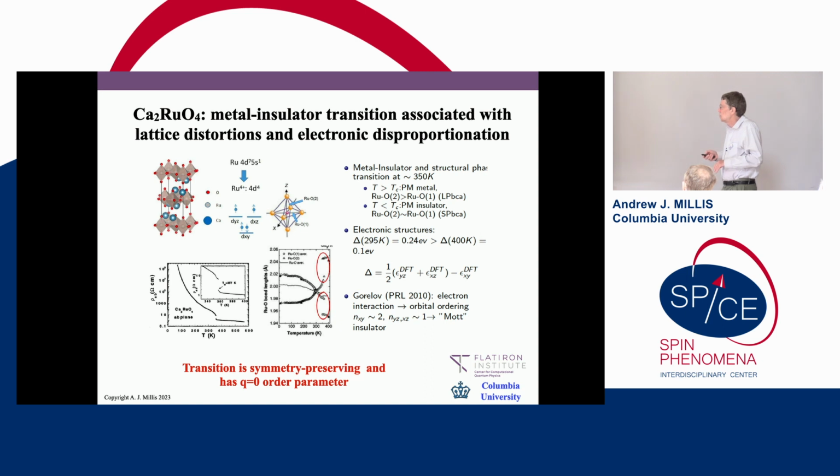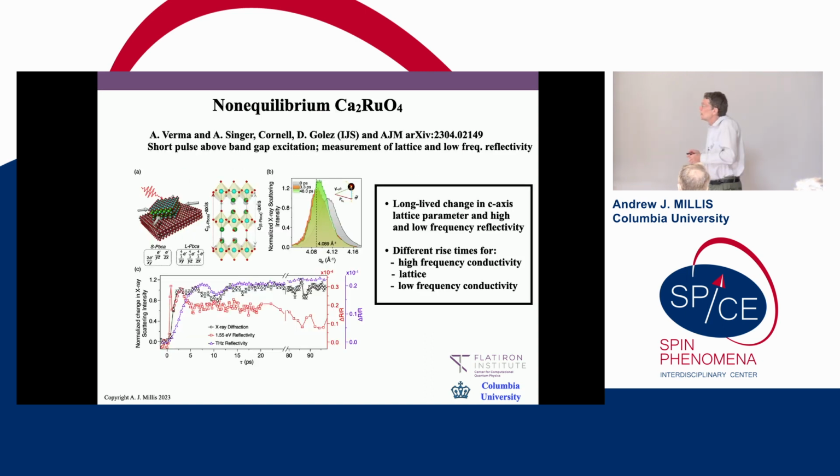Okay, so that's equilibrium. Now, what Andre and his student or postdoc, I forget which, Anita, did, and it's explained in this paper, which is primarily an experimental paper, is again, they excited it, they pumped it with an above bandgap laser at the same 1.5 eV, and they simultaneously measured three things: the transmission at a high energy around the bandgap energy, the transmission at a low energy in the lower terahertz range, and they measured the lattice structure, in particular the c-axis lattice parameter, which is associated with this flattening of the octahedron.